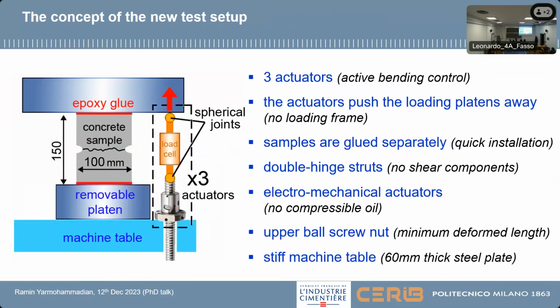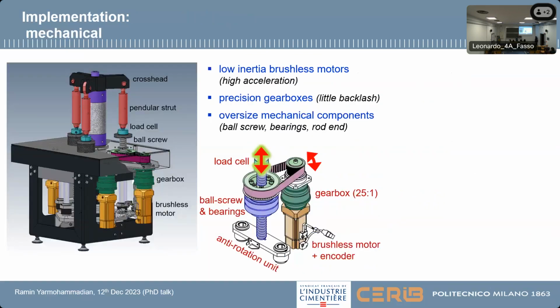We were thinking that we should design a new test setup, and in this new test setup, instead of having one actuator, we need 3 actuators, which can pull concrete from 3 different sides. So if the crack is starting on one side, we can easily understand and compensate it to have a planar crack all around the sample. And then the actuators are pushing 2 platens to reduce the elastic energy stored in the system. And then we decided on a lot of different things to reduce the stored elastic energy again. Like we didn't use compressed oil, we used preloaded ball screw nuts, a stiff machine table, all of those to reduce the elastic strain.